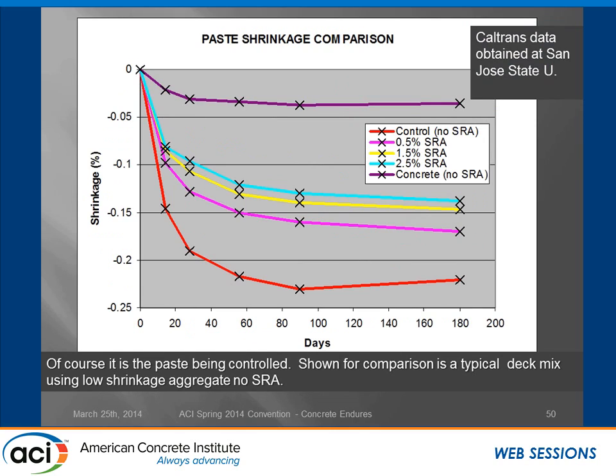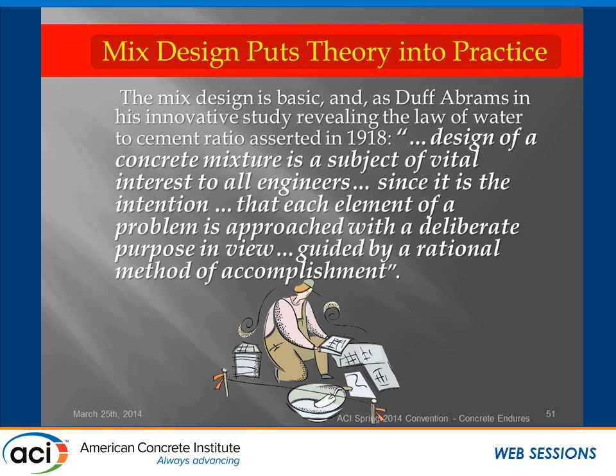We did it on paste. You can see that cut into the paste. The red line on the bottom is with no SRA, and as you add SRA, it gets less and less. The top curve up there is just to get a comparison of how much a paste-only mix shrinks as compared to a typical concrete mix. That was like a 7-sack mix up there.